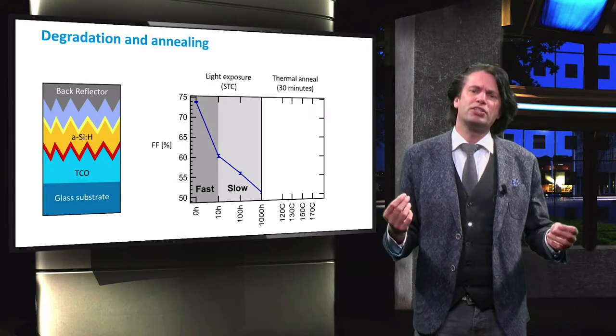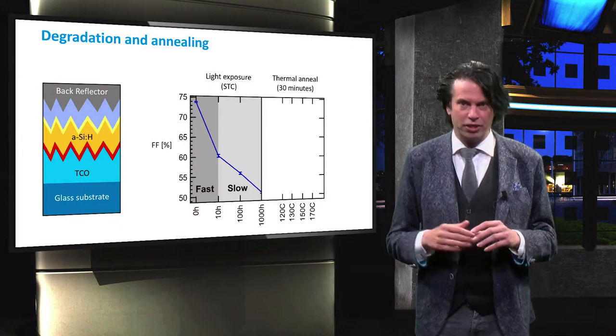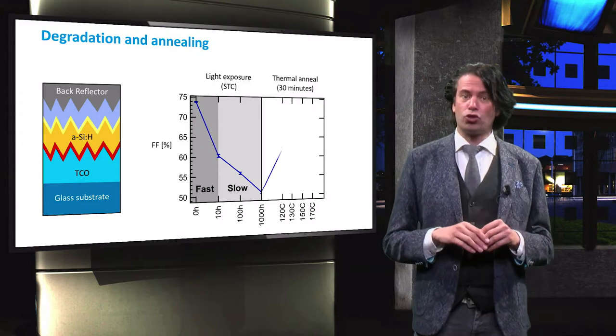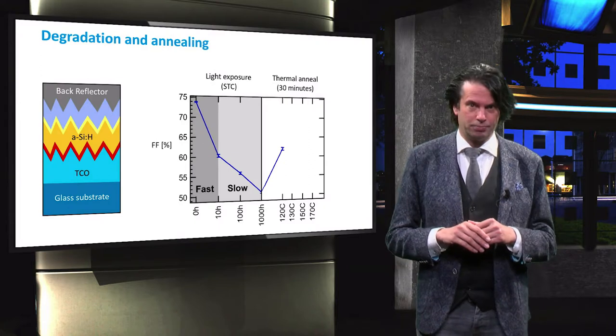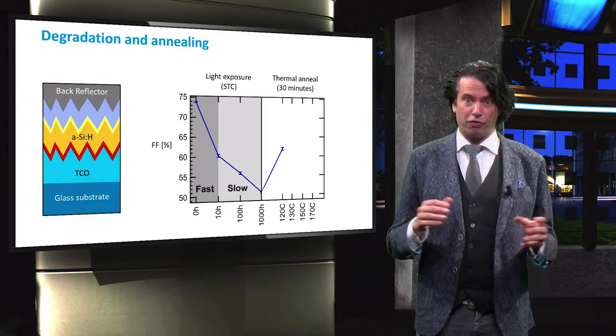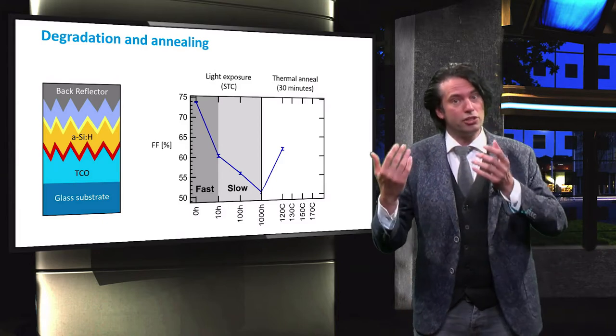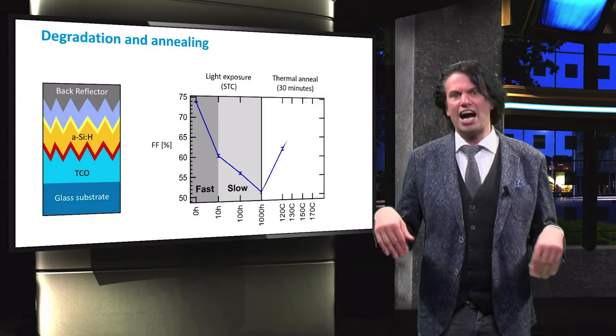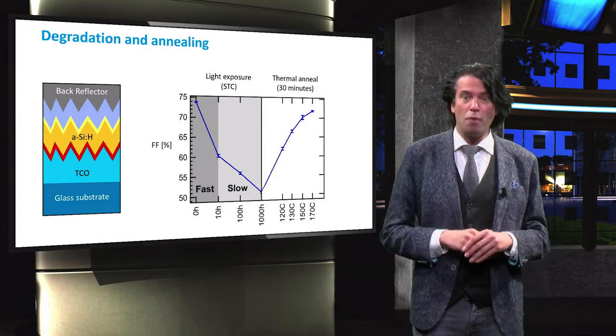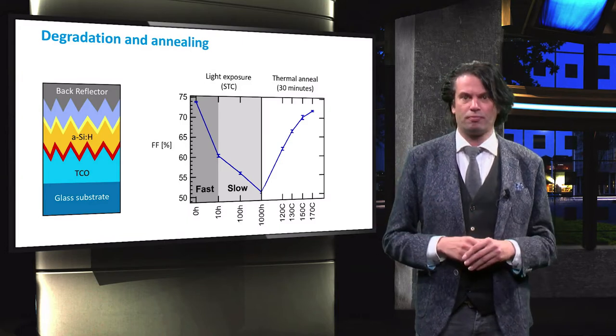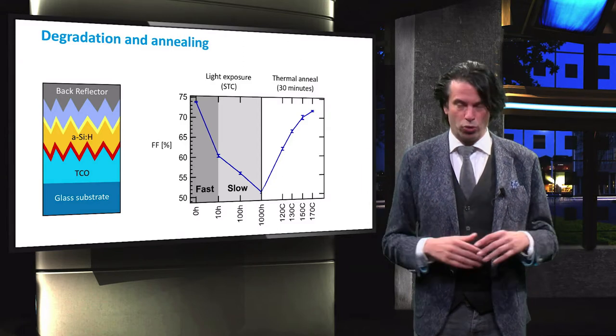An interesting thing happens when the stabilized cell is subjected to a step of thermal annealing. The performance loss of the cell can be reversed to a certain degree when thermally annealed. After 120 degrees Celsius for a period of 30 minutes, the fill factor has been increased from 51 percent to about 62 percent. After higher annealing temperatures, yet more of the light-induced degradation is reversed, up to 97 percent of the initial fill factor. Unfortunately, after annealing the cell will once more degrade when exposed to light.